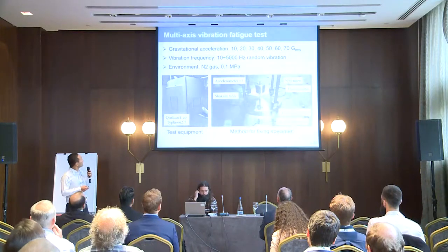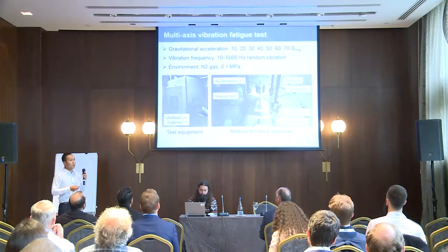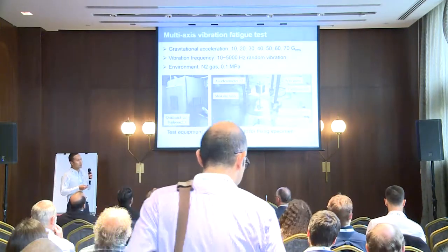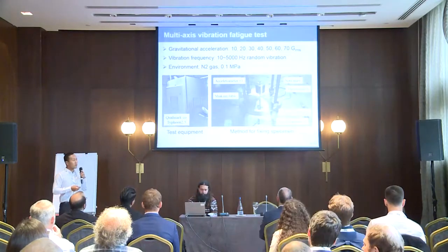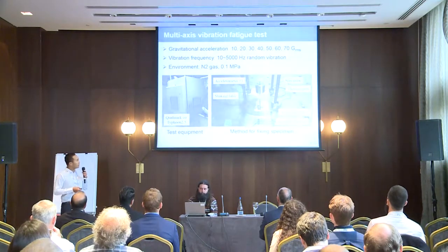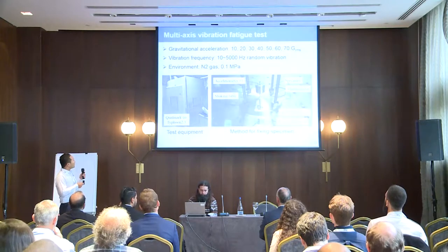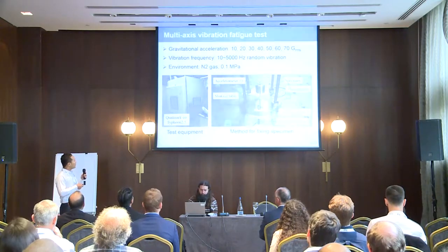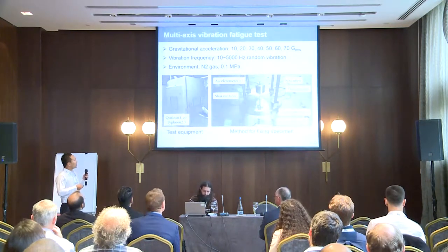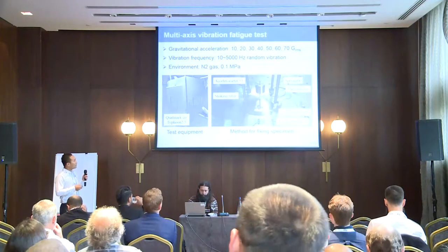We used the weight to break the specimen easily. We conducted the multi-axial vibration fatigue test at seven different gravitational acceleration conditions: 10, 20, 30, 40, 50, 60, and 70 GRMS. The vibration frequency band is 10 to 5,000 Hz, and the environment is nitrogen gas. This test equipment generates multi-axial vibration, and we fixed the specimen to the shaking table using four bolts, and employed three accelerometers and a strain gauge.